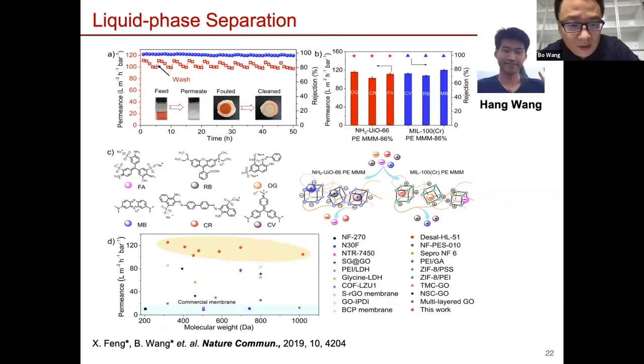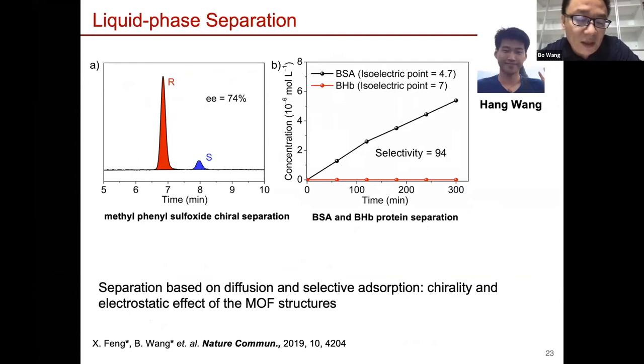And the other membrane we mentioned before, using that hot pressing method with 10 different MOFs, because it's a self-standing membrane, you can see we can separate, of course, according to the pore size, different dye molecules. And when we introduce chirality to the MOF structure, you can even use such a membrane to separate chiral compounds. And also in certain cases, when you're using charged MOF or COF structures, eventually you can separate proteins according to their charge at different pH levels. So you can separate according to the physical properties using such MOF membranes.